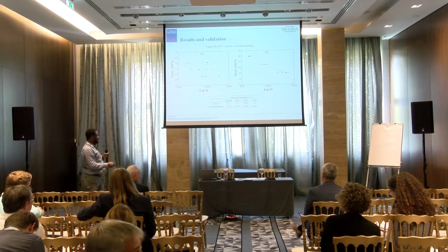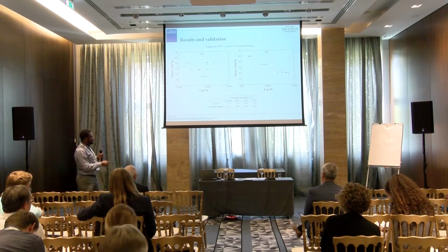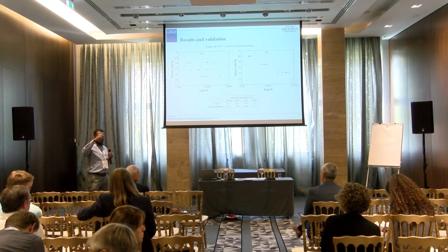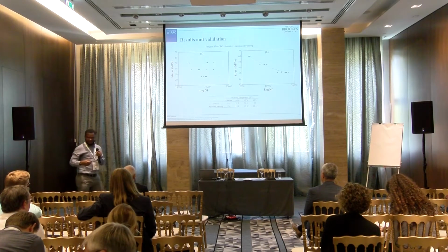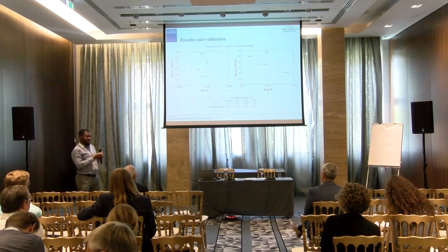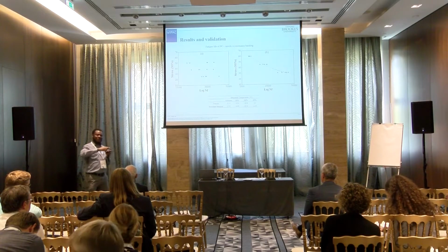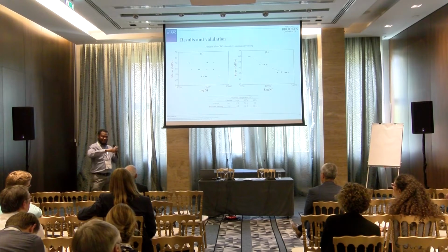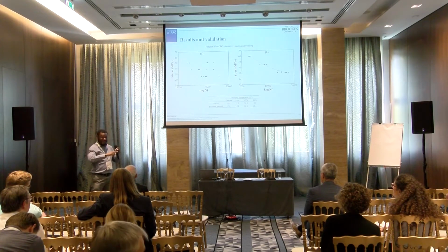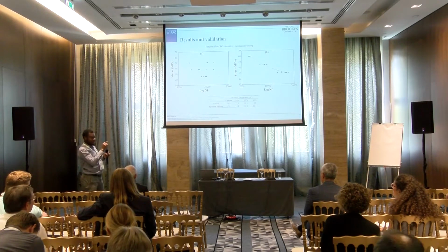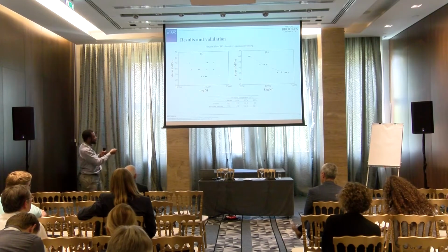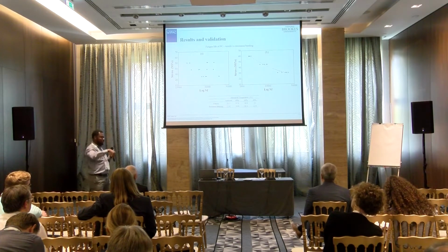If you look here, ambient is 22.6. At 80%, it's actually going down rather than going up. And why has that happened? I think it's called self-induced cooling, okay? If you do like this, you see that it kind of cycles in the air and is cooling your finger, okay? And that's what is going on here. So it is cooling the specimen, and you can see the higher the loading, the further it goes down.